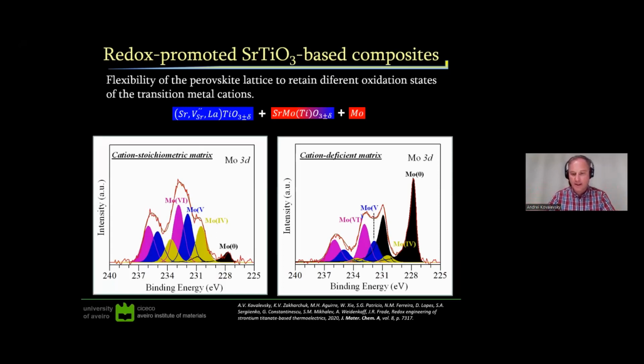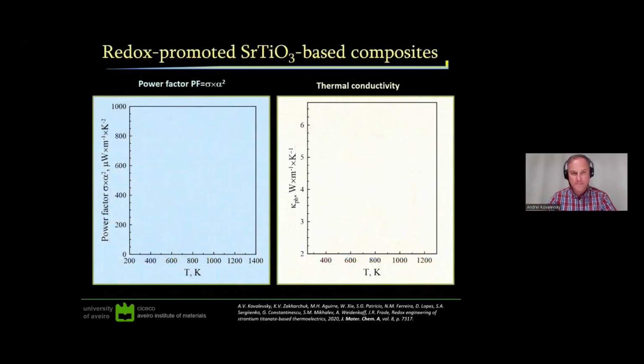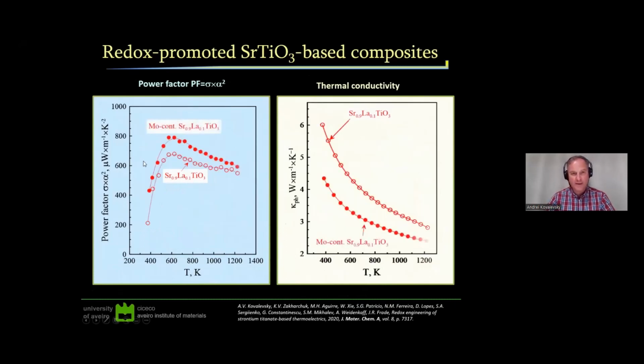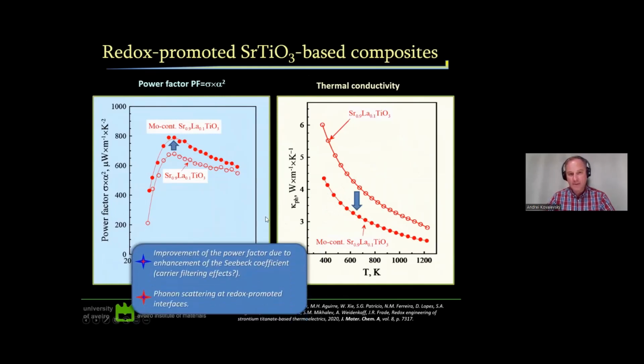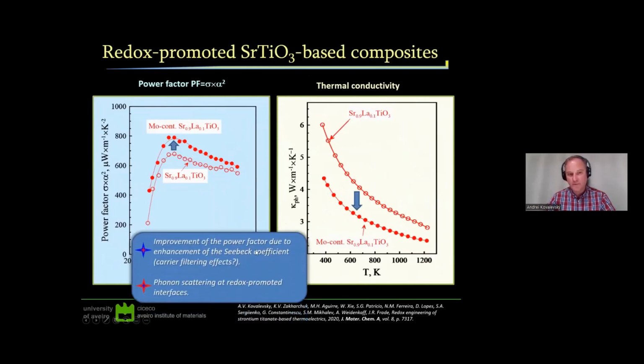And so this has an interesting effect on the thermoelectric performance. I cannot go into a lot of detail here because I don't have a lot of time, but basically, if you compare the matrix itself with pristine material versus matrix with molybdenum addition, we have simultaneous improvement in the power factor and significant decrease in the thermal conductivity. This happens due to enhancement of the Seebeck coefficient from carrier filtering effects, we think.